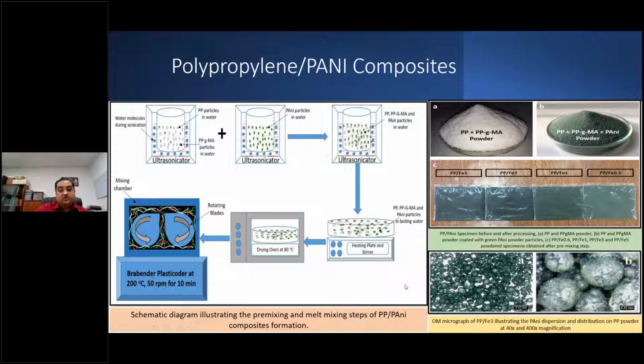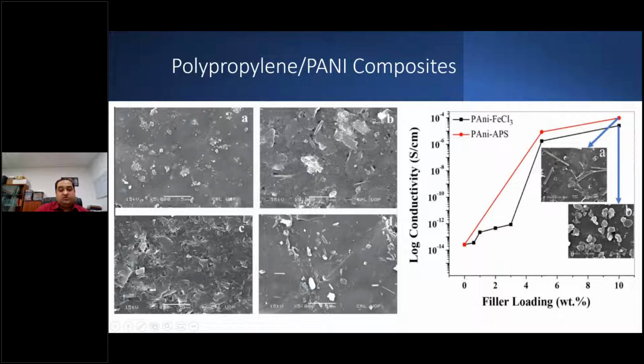But once again, through SEM, we were able to generate the result at very high weight fraction. We were able to see some of the agglomeration, but generally speaking, we get good dispersion and distribution, and once again, it led towards the formation of enhanced conductivity in our product.